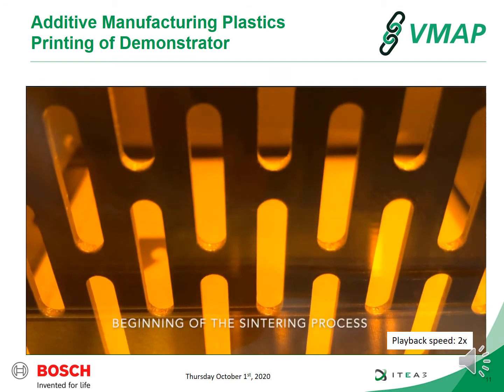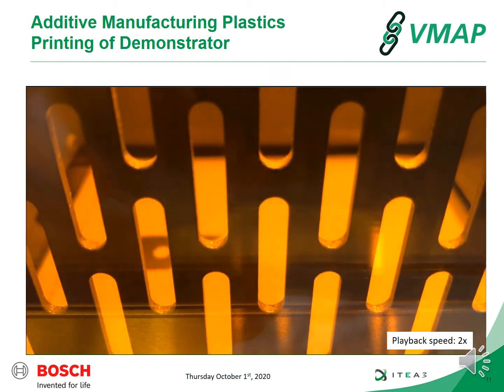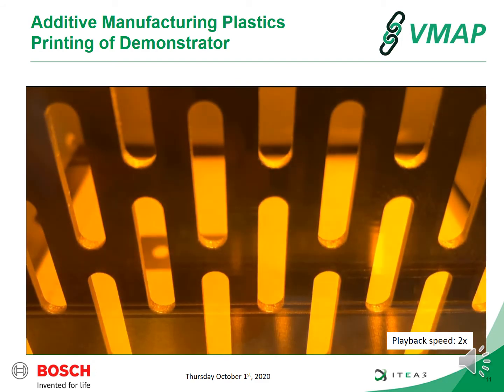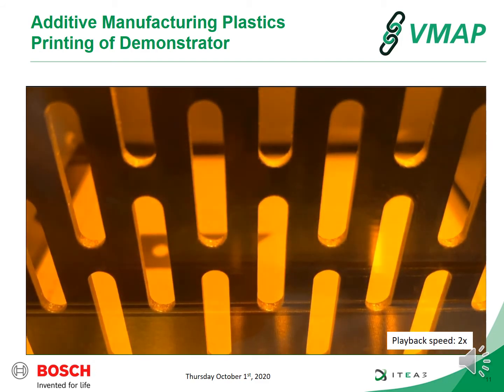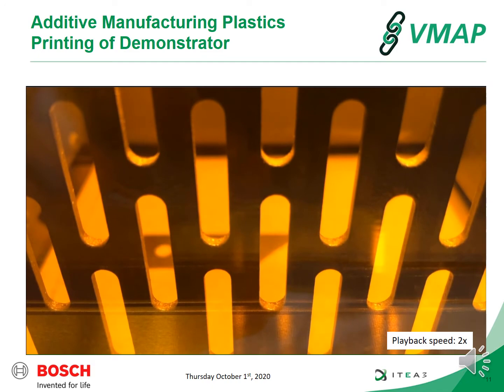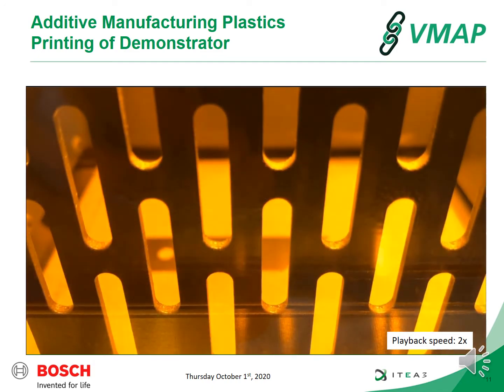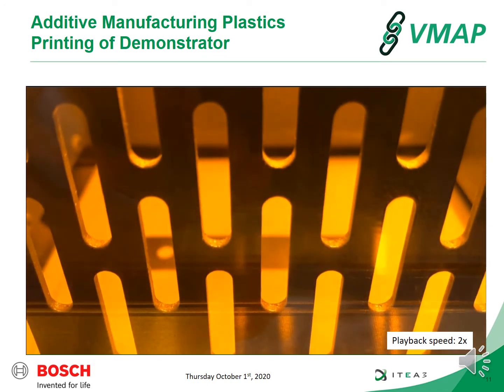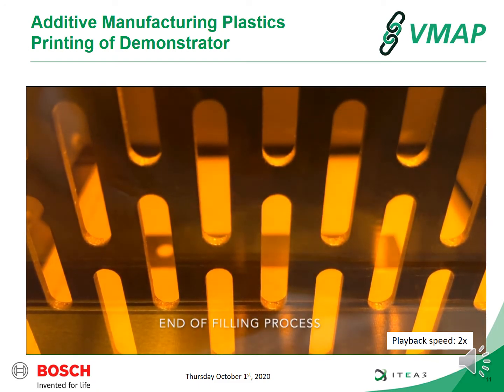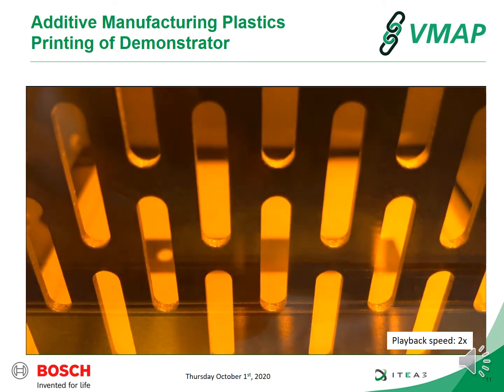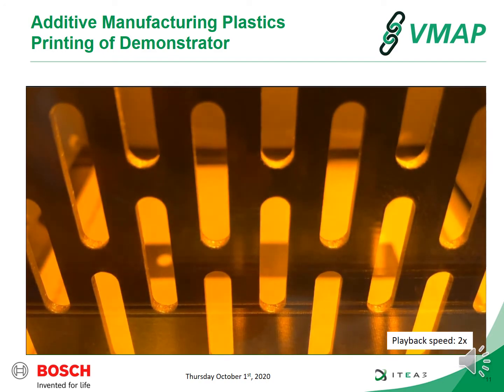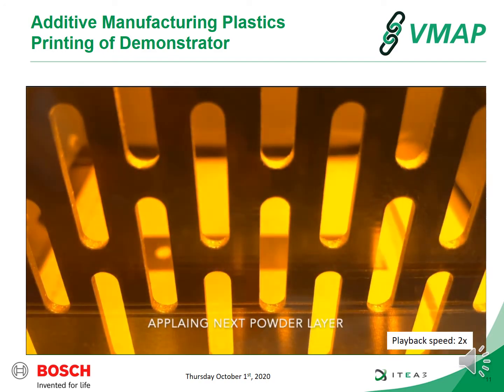In this video, we can see how a printing process on the Sintratec S1 proceeds. The build chamber is protected by a metallic grid, and you can see the progress of the lasering beyond this grid. A warpage plate is printed with a hatch angle of 45 degrees from the left to the right. The temperature of the layer is being actively controlled by infrared lamps, which modulate their intensity accordingly. Once the sintering layer is completed, the laser proceeds in refining the edges until the piston prepares for application of the next powder layer.